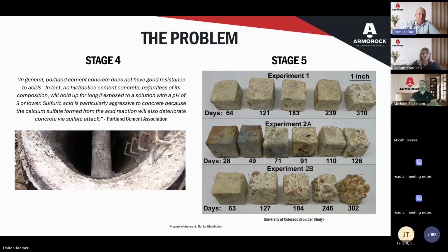So sulfuric acid, pH of 1, much lower than the 3 or lower in this statement. And then the calcium sulfate, that's the white powdery substance, gypsum, that you see in the picture. This is dangerous and leads to a snowballing reaction because it expands, chips away, spalls away the concrete structure, exposing more concrete to acidic attack from the Thiobacillus and sulfuric acid.